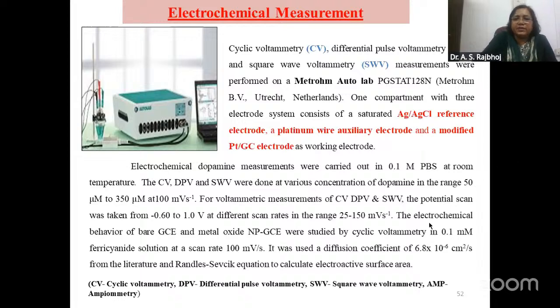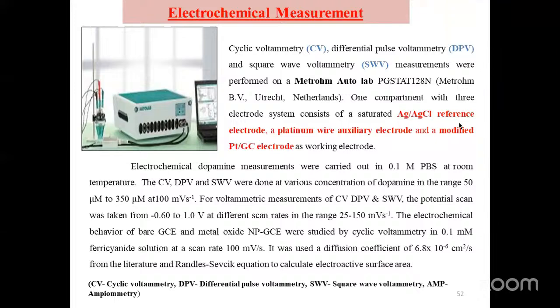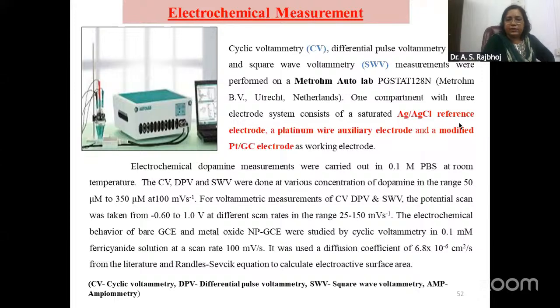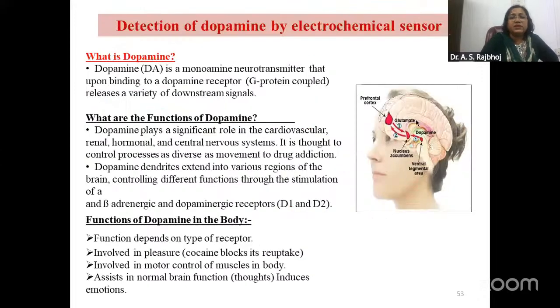So voltammetric studies have been done. The potential scan was taken from minus 0.6 to 1.0 volts at different scan rates in the range of 25 to 150. So this is what we have done here, and we have studied the dopamine. Then we have the sensing of dopamine. Now, why have we done the sensing of dopamine?